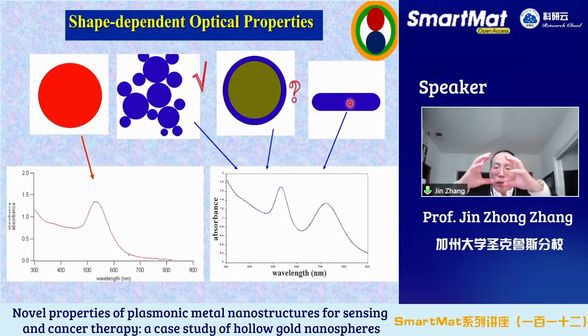Of course, for spherical particles, all the modes are degenerate. No matter which polarization you use for light, in any direction, it's all degenerate, which is why we only have one peak. These have two modes or two peaks. Well, should we have two peaks with a core shell? Many thought so. I also thought so, because there's a lot of literature that claims so. But I can tell you today, that's not the case. If you really have a core shell like this, you should not see two peaks. You should see one, as I'll convince you in a minute.